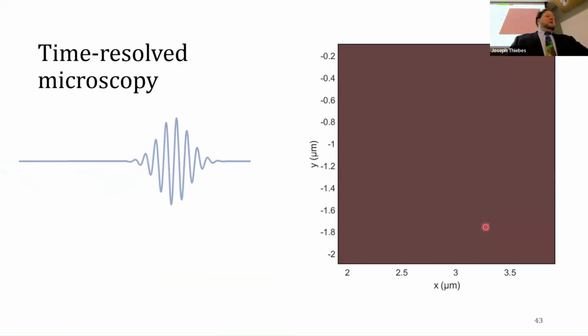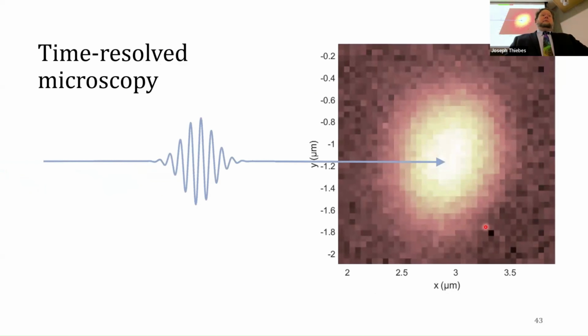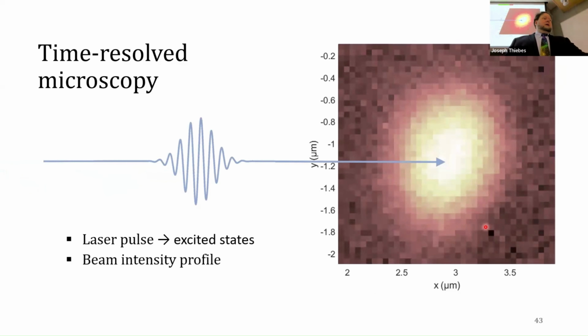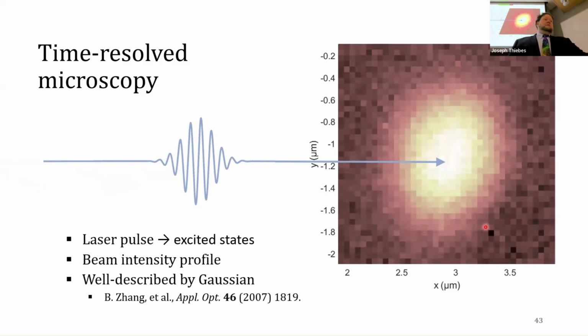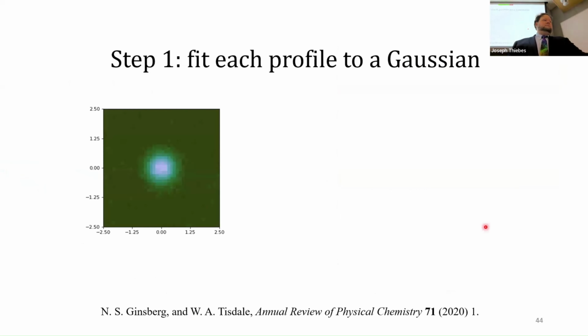And so just again, a quick recap, we photoexcite a population of excited states. And then the intensity of the laser pulse is going to be proportional to the population of excited states. So if the laser pulse is well characterized by a Gaussian function, then so too will the excited state population be. And that has been found to be the case. If you have a well-focused laser, you will have a Gaussian approximate distribution of excited states.